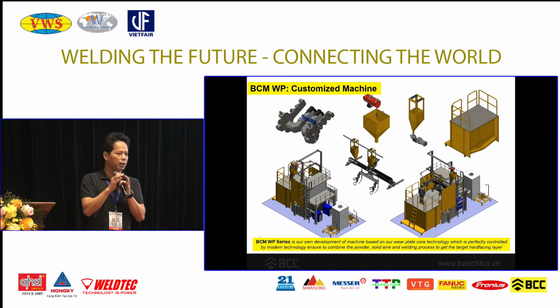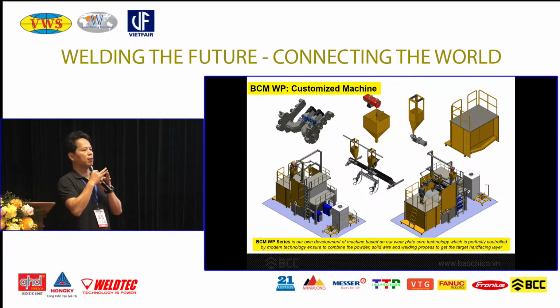like chromium carbide. But if we come to some industry like power or steel making, it's not only abrasion, it also has corrosion, also has heat as well. So we had to add niobium or some other factor, depending on the requirement. So it's very flexible how we can create the formulation of the powder. So we have the formulation.